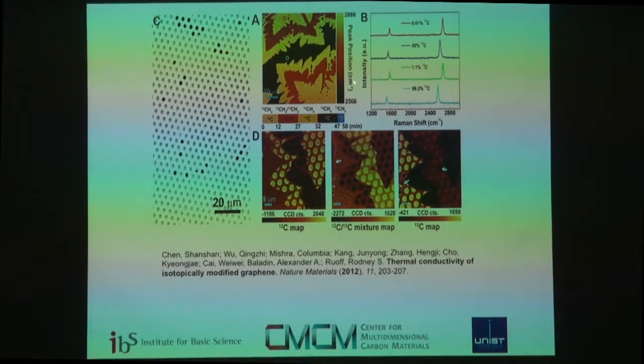And so with these larger crystals, it's then trivial with the micro-Raman mapping method to know which isotopically labeled graphene you're dealing with. So as we're growing, we're controlling the flow controllers so that we're controlling whether we're putting in 99.99% C12 or a 50-50 mix or normal methane or inverse normal methane where it's mostly C13 but 0.8% C12.